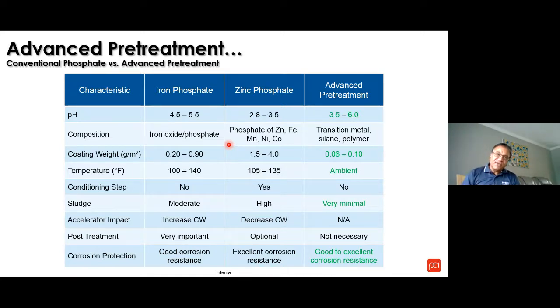As you see in a zinc phosphate, prior to the zinc phosphate, you have a conditioner stage, and in the post-treatment, you have the final seal stage. So after the cleaner, you have 3 additional stages. If you go with the zirconium pretreatment, there is no need for final seal. So you talk about only 2 chemical steps, cleaner as well as the zirconium pretreatment, versus potentially 4 in a zinc phosphate, which is the cleaner, conditioner, which is a grain refiner, zinc phosphate, and final seal. If you are replacing the iron phosphate, typically it's a cleaner, iron phosphate, and final seal. Instead of 3 chemical stages, you will be going with only 2, cleaner and the zirconium pretreatment.